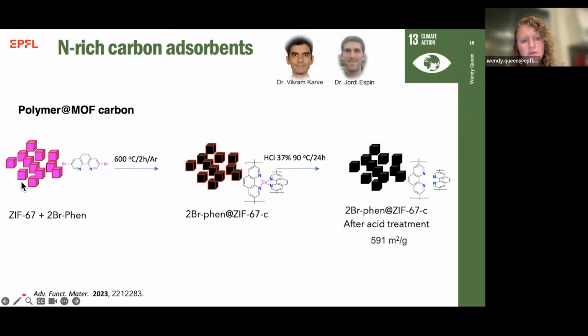So what we've done is we've taken a MOF. We simply put this small molecule, which is a bromophenanthroline, inside the MOF, and then we pyrolyzed it. So this is how you produce carbons. What happens is during the pyrolysis process, this small molecule cross-links to form polymers inside the pores, and this is driven by the cobalt, which is the building unit in the MOF. And so then after we make the carbon, we treat it with an acid, we release the cobalt, and we can reuse that, for instance, for MOF synthesis.